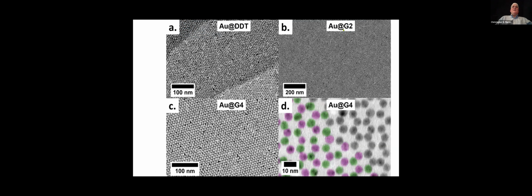And so you can see here in a generation 2 dendrimer where there's quite close packing possible because the ligands are not that bulky yet. But by the time you get to G4, generation 4 in the branching, now you have a much more open framework which the particles can adopt with the spaces that you see here in the electron micrographs in between them not being empty space, but now occupied by the organic subphase of the dendrimeric material, which is actually a significant portion at this point of the total volume.